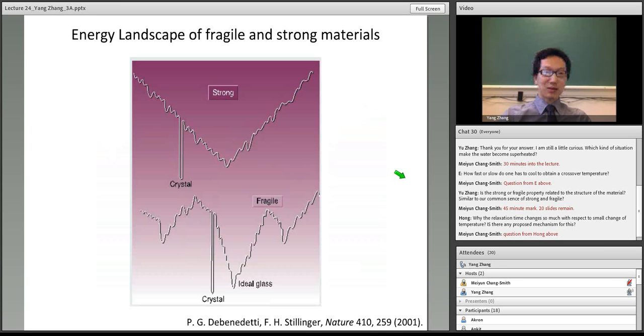So this energy landscape, roughly speaking, gives us a very good explanation of the previous phenomena that we have talked about. For strong material, you can see the energy landscape is rough, but more or less with a constant activation energy. But for fragile material, the activation energy is temperature dependent. And the ideal glass corresponds to this transition that happens above the Kauzmann temperature. And then we have very sharp crystals.